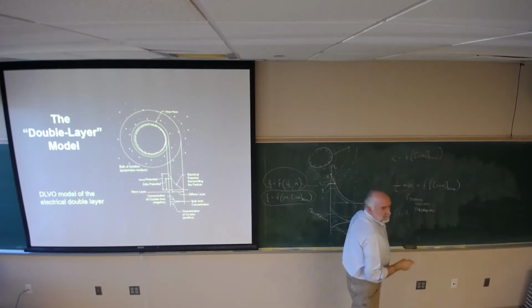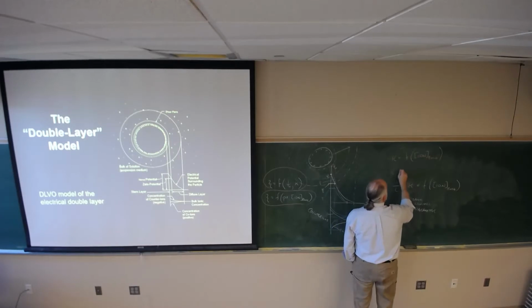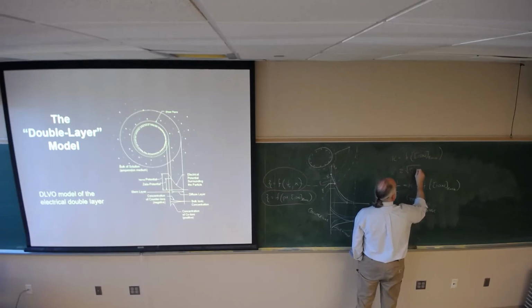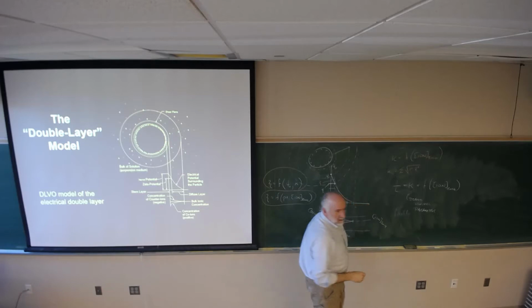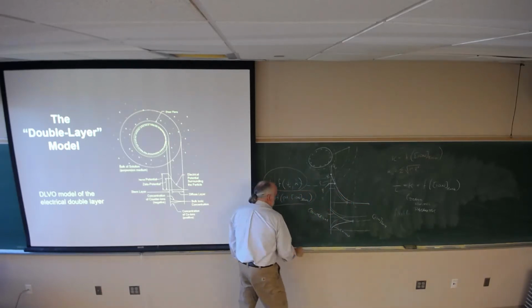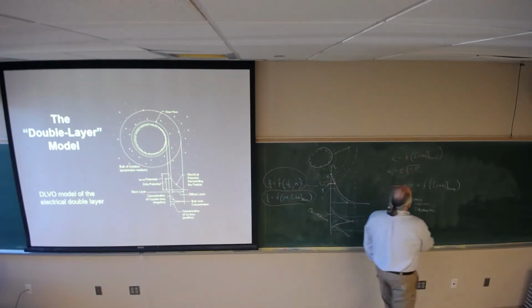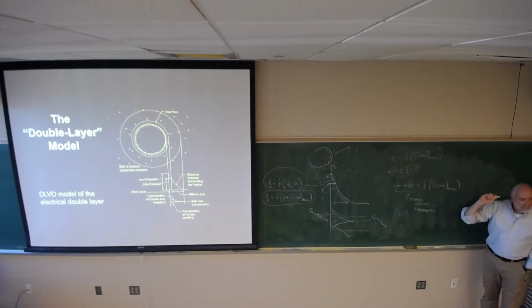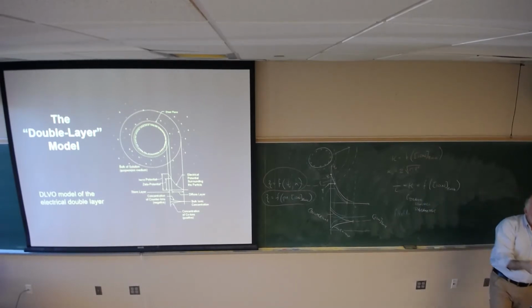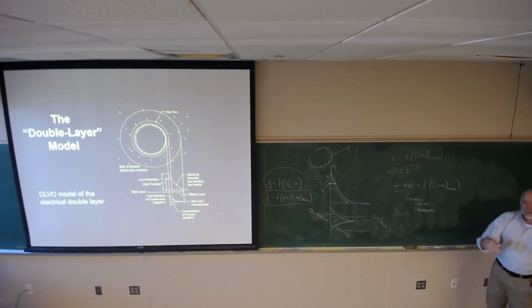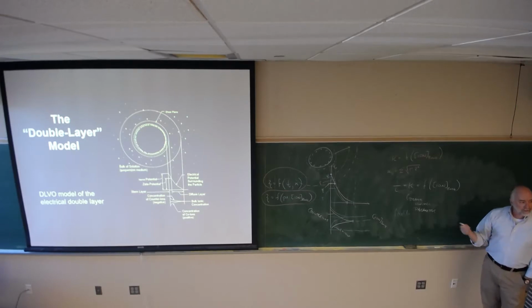That is defined as this: the summation of the square root of C sub i, z sub i squared, is kappa. Okay? So what that means is that I do not care about the sign of the charge, because the charge is squared. If I have -2, it's the equivalent of +2. So it doesn't make any difference what the charge is on the ion that's coming in, positive or negative. The magnitude of that charge makes a difference.